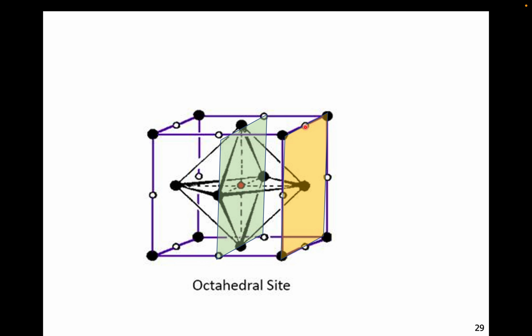But usually this is extended plane, so I also have the other one here. And this is bottom, I also have the other one at the top. So it's 4 possible jumping directions. Z equals 4. But I need to check whether this one is 4. It would be better if you can check each one, but I just check this one.